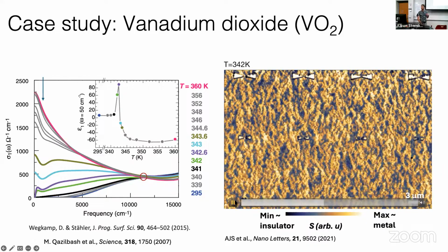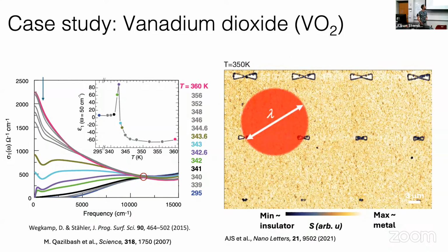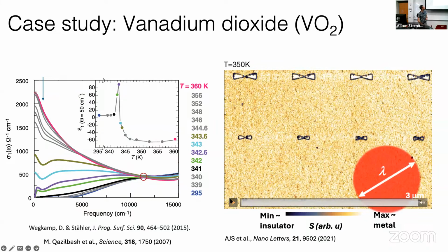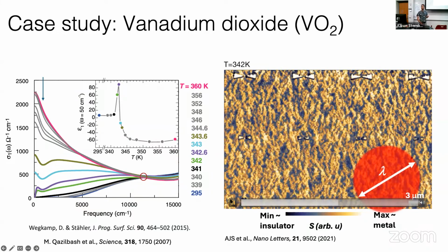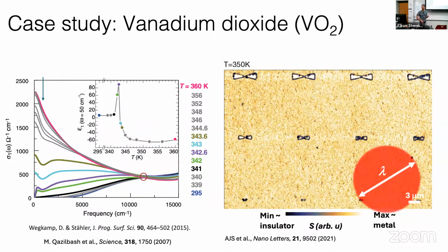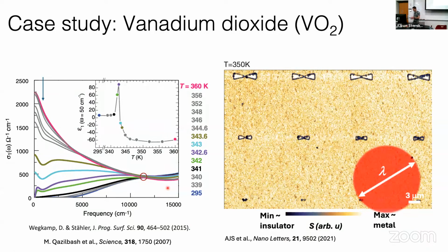This does not happen homogeneously. So we see droplets of metal that grow and coalesce, and the size of these droplets is subdiffraction limited. So we would be blind to all of this with far field optics, demanding this near field approach. So all of this was done and known back in 2007. So this was the work of M. Qazilbash, although I'm showing my own data.